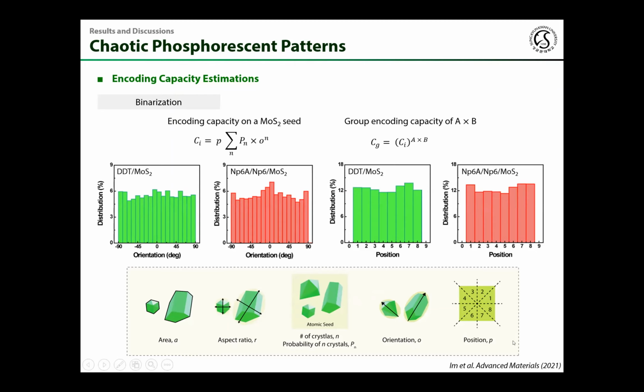Among these parameters, the orientation and position have a flat distribution like this. This flat distribution can boost the encoding capacity for one MoS2 seed. In addition, the number of crystals and its probability also exponentiate this encoding capacity. Moreover, if I want to make a large-scale security label with an A by B array, the group encoding capacity exponentially increases. Through these formulas, I could estimate that a 1 millimeter scale Np6A and Np6 MoS2 pattern can contain more than 10 to the power of 70,000 encoding capacities.